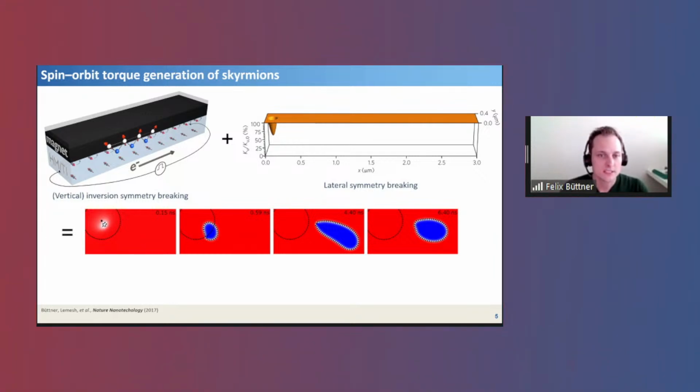If you combine this and then inject a current pulse exceeding a certain threshold amplitude, you will see that you actually switch locally the magnetization from up to down near that defect, where the necessary in-plane field provided for this spin orbit switching is provided by the Dzyaloshinskii-Moriya interaction. By continuing to apply this current pulse, you can move away this locally switched area, which is not yet a topological object, but rather just a magnetic bubble.